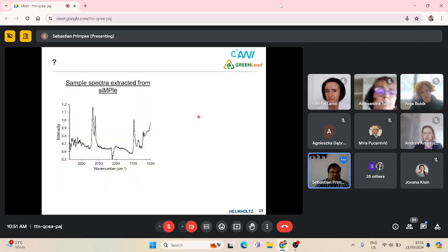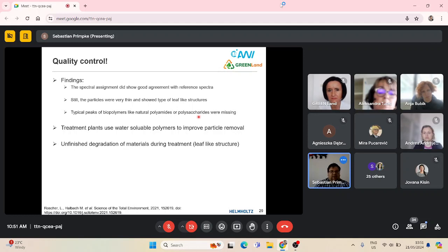So for quality control, we checked the spectra. They looked, not surprisingly, as expected for this polymer type. Then we checked against the database, and all was fine. Still, we figured there might be a leaf-like structure in this sample, but we didn't find any typical peaks of biopolymers, like natural polyamides or polysaccharides. So it was not fitting any expectation of a biopolymer. One of the things we thought about is polyacrylamides, which are heavily used in wastewater treatment plants as water-soluble polymers to promote the precipitation of all the solid materials.